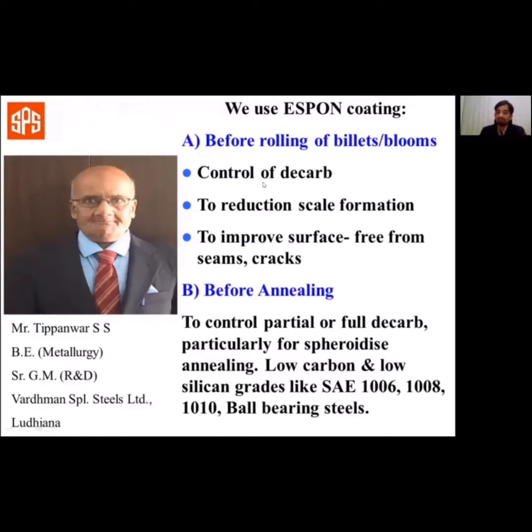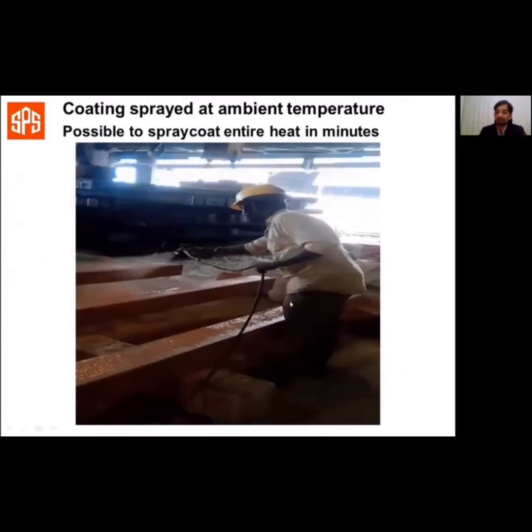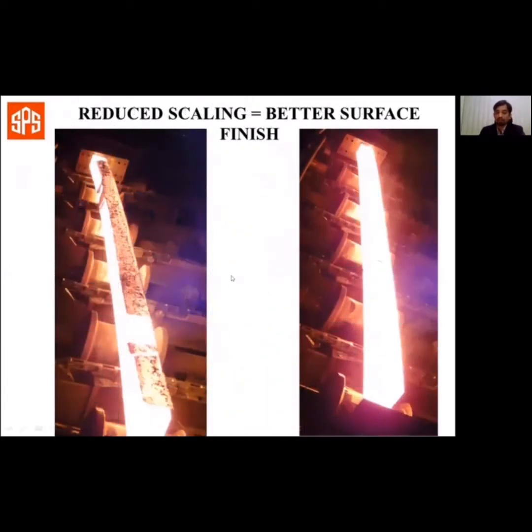Billet heating to control decarb, reduce scale formation, and improve the surface finish, and also before annealing to control partial or full decarb on the grades that he's mentioned here. Coating can be sprayed at ambient temperature as shown in this picture here. Very less time is required to coat the entire heat.